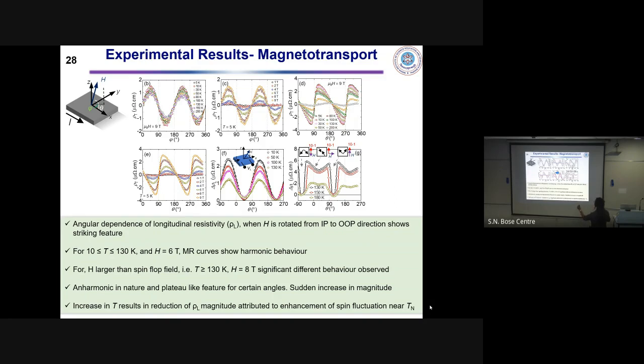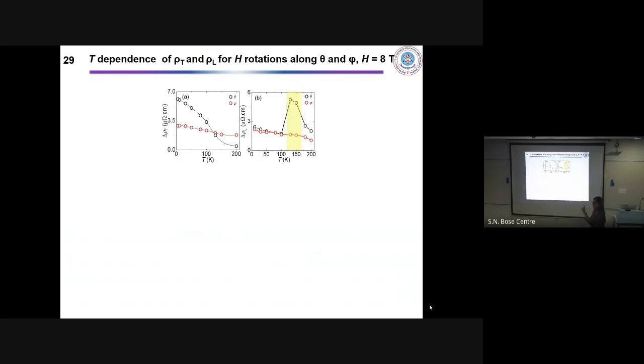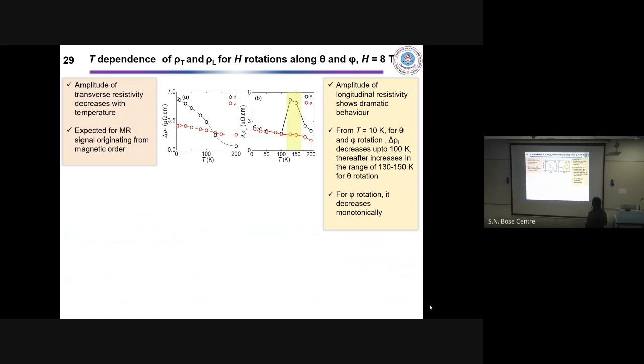In order to understand that, we further extracted the amplitudes of the resistances that we measured. This is the amplitude of the transverse resistivity. It decreases with temperature for both theta and phi rotation, and this is expected for a magnetoresistance signal originating from magnetic order. However, when we checked the amplitude of longitudinal resistivity versus temperature, for phi rotation it decreases monotonically. For theta rotation, up to 100 Kelvin both of them match, but in a temperature window of 130 to 150 Kelvin, there is a sudden increment in this delta rho L.